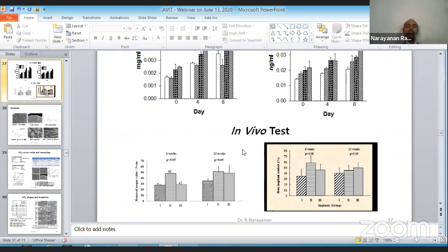It has been shown that the performance of the oxide coated titanium is better after 6 weeks and 12 weeks. So what do you measure here? You place the sample inside the body for a certain predetermined time, say 6 weeks or 12 weeks. After this time period is over, you sacrifice the animals and cut a small portion, and you can see whether this metal is very rigid or not. So you can use the removal torque values. You can see that the removal torque values are high for the anodic oxides. So this way you can ensure that these oxide coated pieces are stable and rigid and attach very firmly with the bone. So this is one way of test.